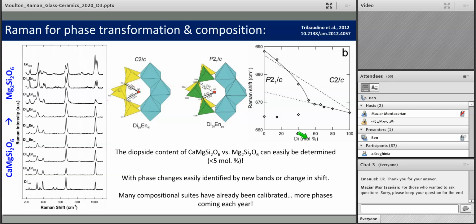If you're interested in super strong ceramics, such as enstatite-based ceramics, Tribaudino et al. a few years back took Raman spectra going from the diopside composition to the enstatite composition, and they showed that as you substitute magnesium for the calcium in the modifier site, at some point the magnesium's too small and the chains kink. And so as a result, you reduce the symmetry, and these enstatite-rich phases have a P2-1/c symmetry, whereas the diopside phases have a C2/c symmetry.